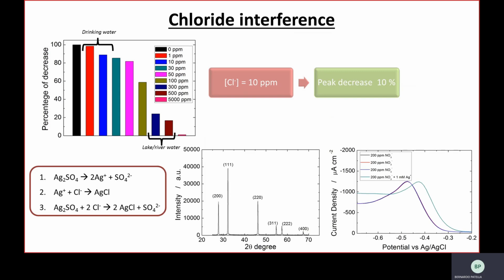Here we show a possibility: to add silver sulfate to the solution. In this way, silver reacts with chloride, producing silver chloride. This is an almost insoluble compound that so precipitates. This precipitate has been collected, and the XRD shows the presence of pure silver chloride. Furthermore, it's important to show that the presence of some silver trace, in this case 1 millimolar of silver, doesn't produce any interference in terms of peak intensity, but just a shift of peak potential towards more anodic potential.